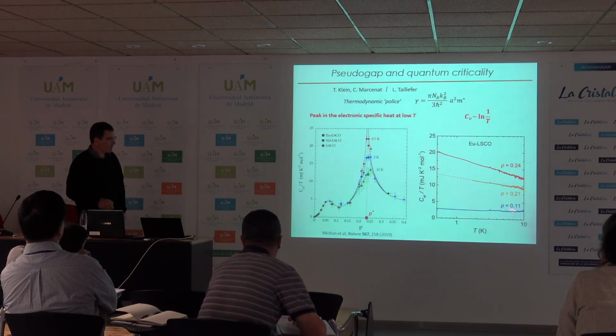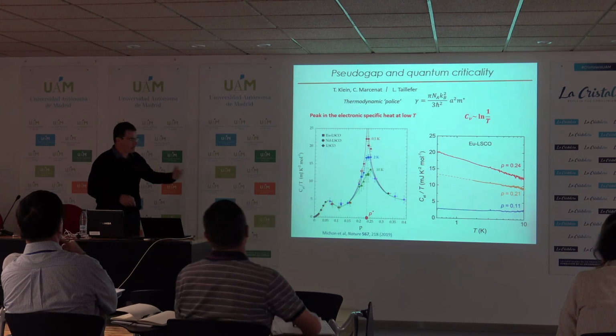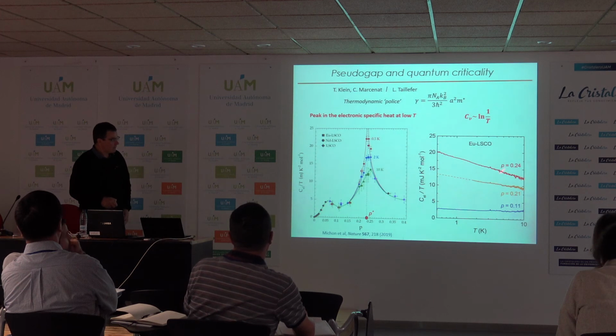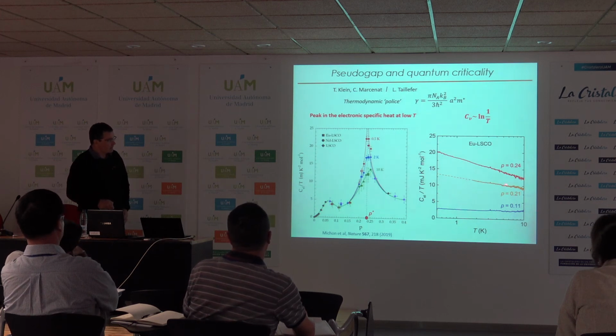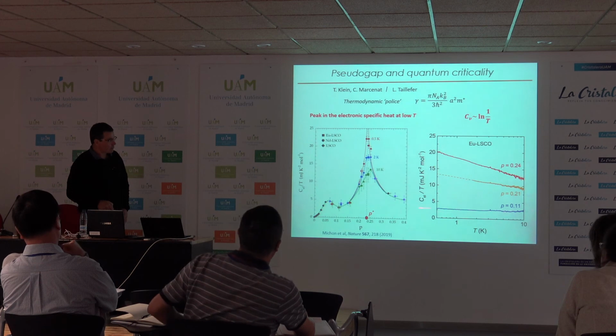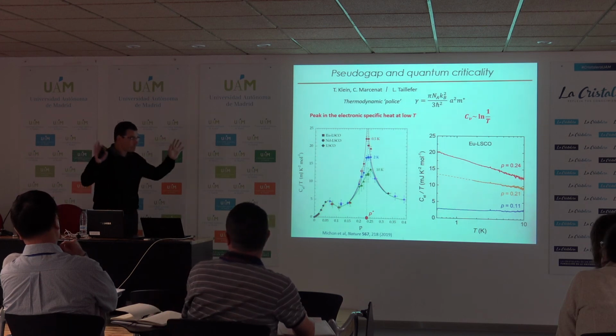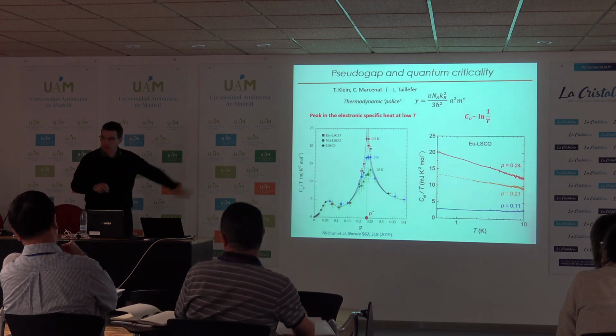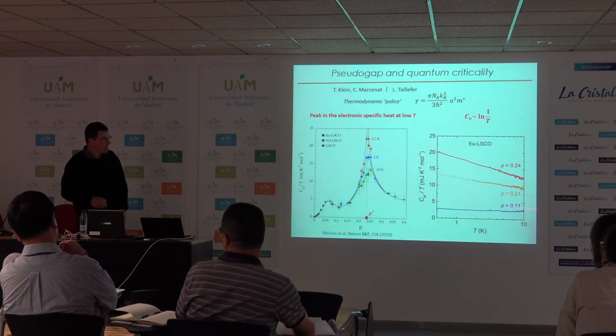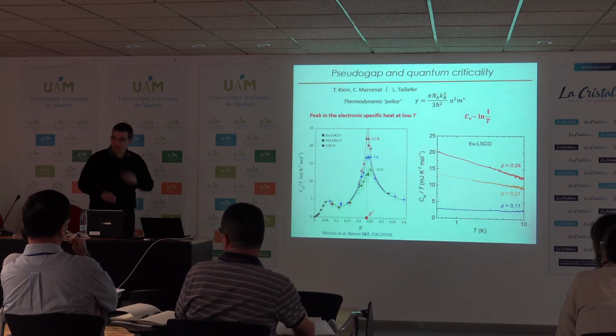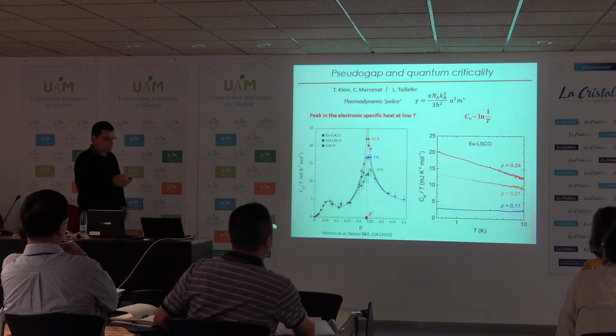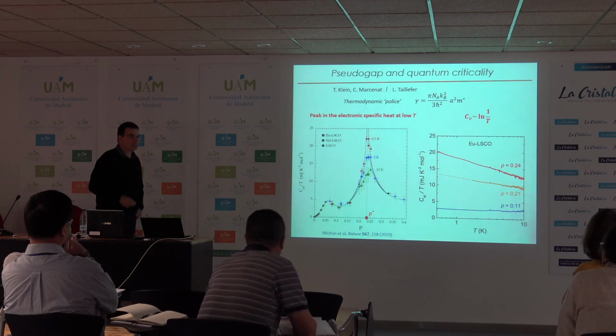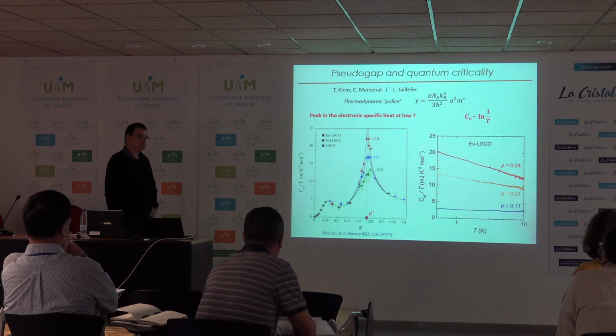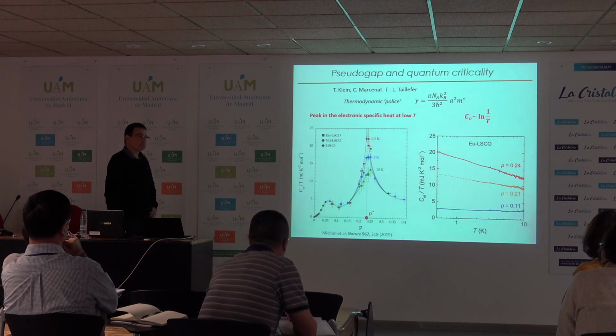So basically, what they did is that they have sampled from the same grower at different doping, and they subtract the curve compared to a sample where it's believed to be very far from the quantum critical point. So this is the subtraction with the reference sample. So it's a sort of differential. Yeah, subtraction. The slope of the logarithm for these two values, 24 and 21, the coefficient seems to be different. Yeah, that's true.